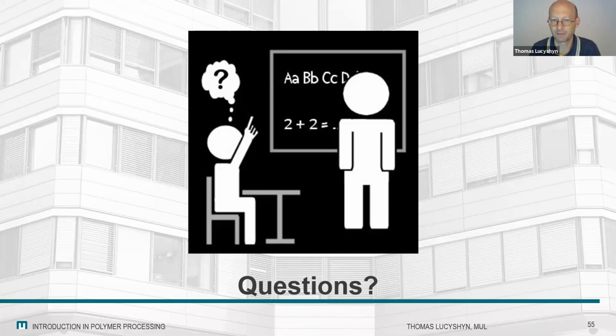And from the viewpoint of a processor, the best you would get is a material with very, very constant flow properties. And that's also the challenge regarding recycling. As soon as we're getting mixtures of different materials, with different flow behaviors, our machines are really optimized for homogeneous materials. As soon as the material starts to be inhomogeneous, our processes will not run in the intended way.